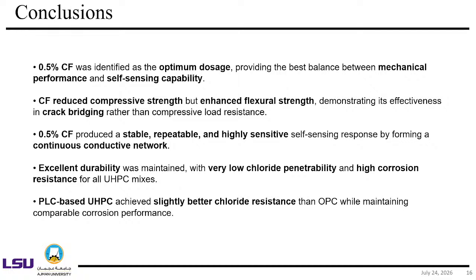It reduced compressive strength a little bit, but it increased the flexural strength. It did form a stable, repeatable, and highly sensitive self-sensing network, which is really good. Excellent durability. So this mix has high potential.